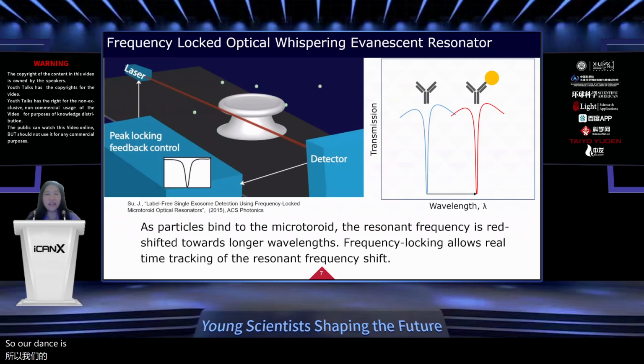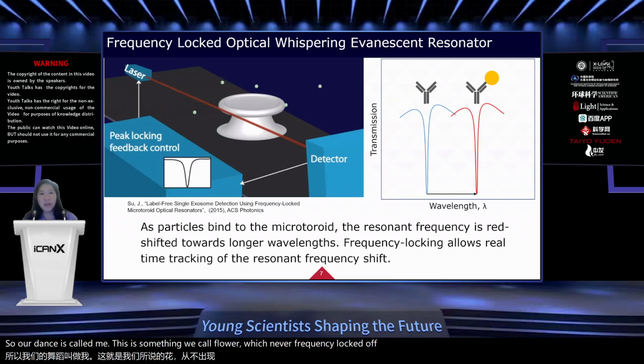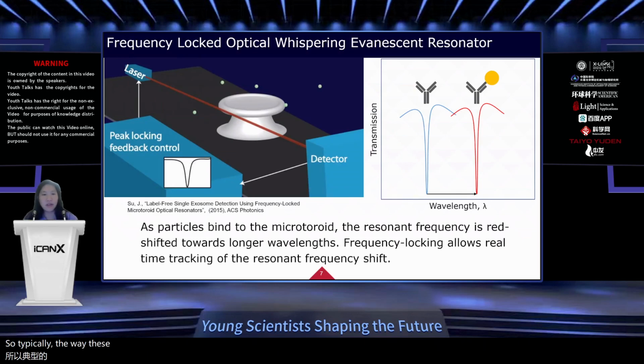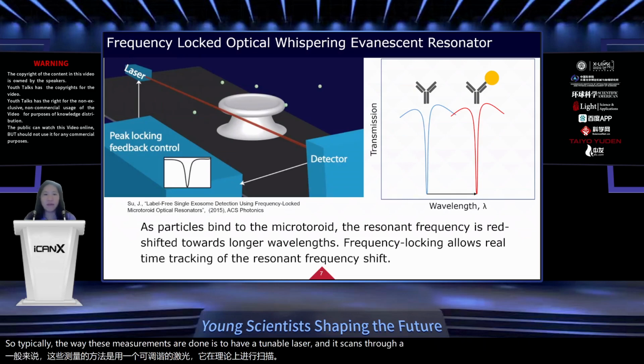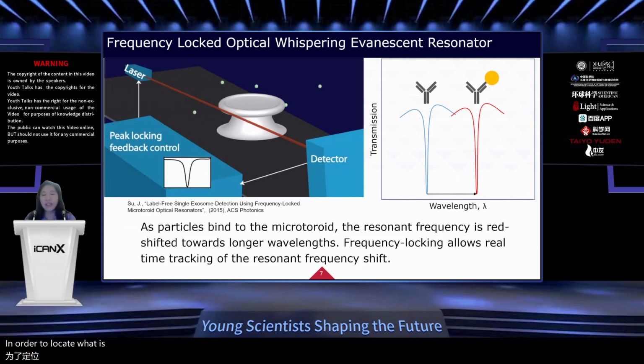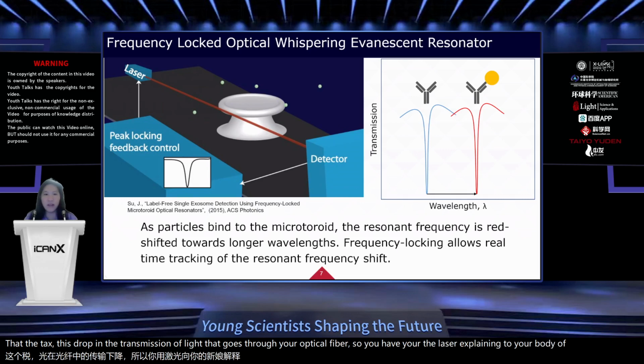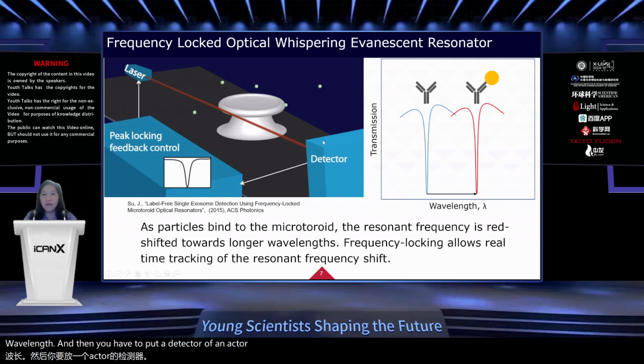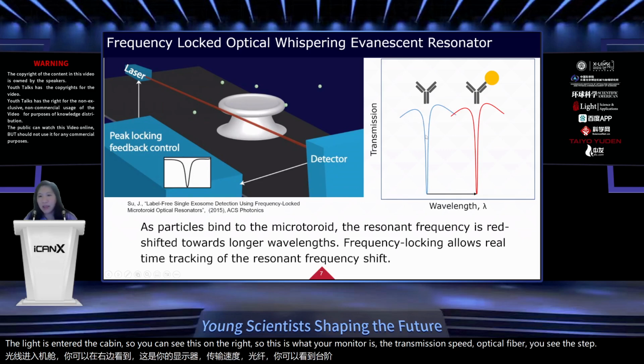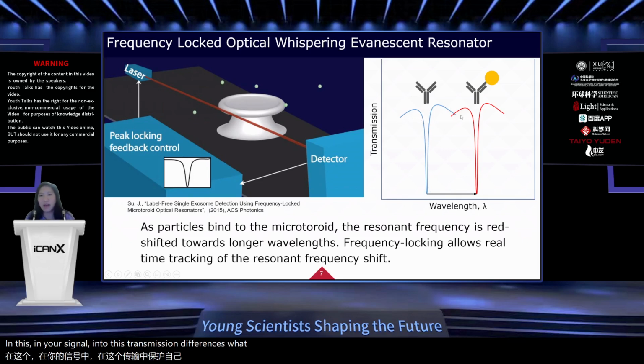Our advance is something we call FLOWER, which stands for Frequency Locked Optical Whispering Evanescent Resonator. Typically, the way these measurements are done is you have a tunable laser that scans through a variety of wavelengths in order to locate the resonance frequency of this cavity. Then you have a photodetector that detects the drop in the transmission of light through your optical fiber. At your resonance wavelength, you see a drop in the transmission because the light is entering the cavity. You can see this on the right. This is what you're monitoring, the transmission through the optical fiber. You see this transmission dip, and this is what you're monitoring as things bind.